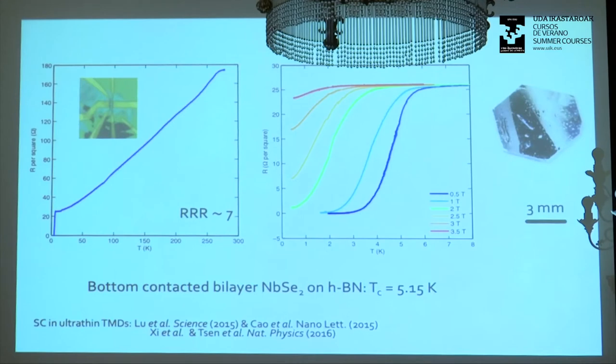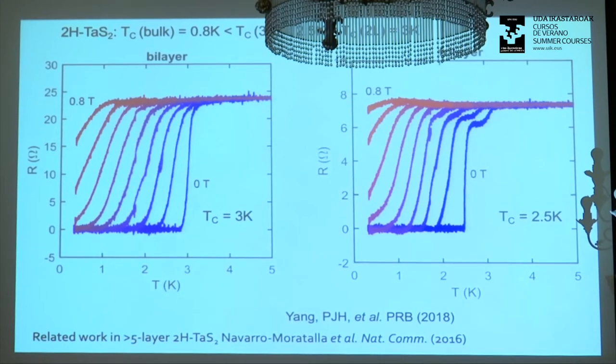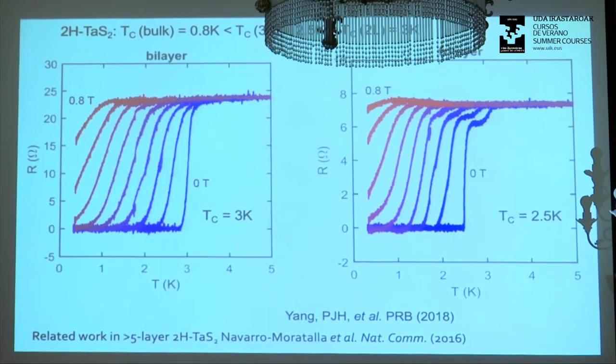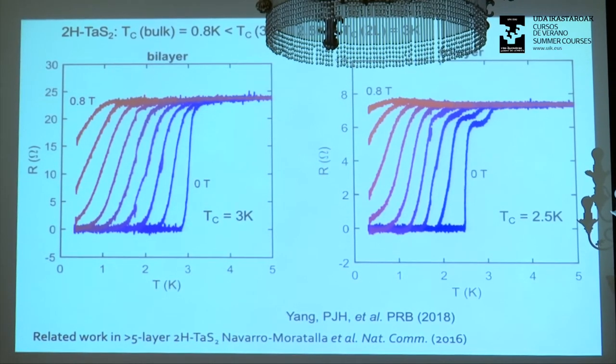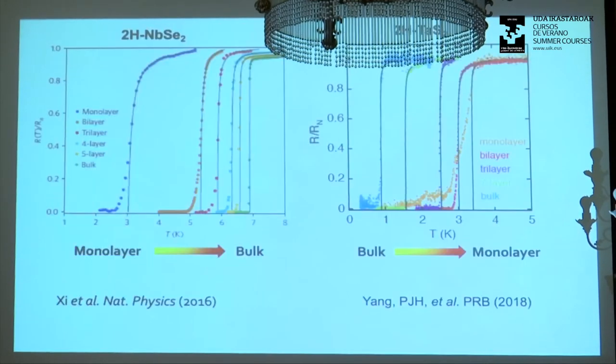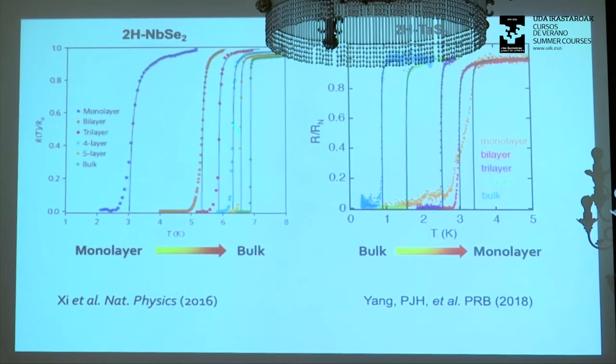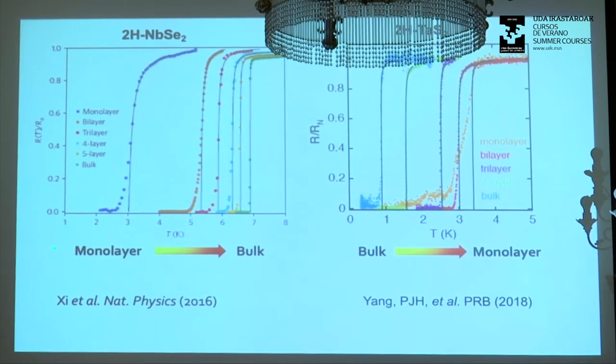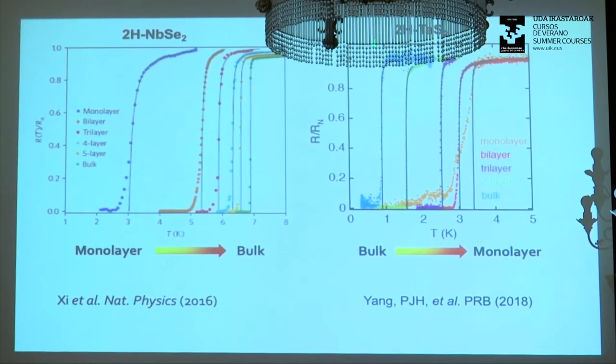You can, on the other hand, have systems like 2H tantalum disulfide. The bulk TC is 0.8 Kelvin, but if you make a three-layer device, TC is 2.5 Kelvin. If you make a two-layer device, TC is 3 Kelvin. Monolayer is about 3.5 Kelvin. So TC nearly quadruples as you make it thinner, okay? And this is something that is very special. Here I have a comparison between published data, I think this is Kin Fai Mak's group, on 2H niobium diselenide, where from monolayer to the bulk TC increases. In our data on 2H tantalum disulfide it is the opposite. From monolayer to the bulk, TC decreases, or from bulk to monolayer, TC increases. Okay? So these two-dimensional superconductors are...